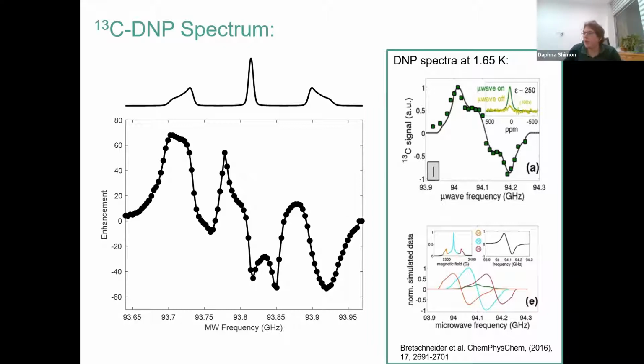And in order to understand the shape of that DNP spectrum, they were able to fit it to solid effect mechanisms from each EPR line. So you see here the blue, the central EPR line has a blue solid effect. The orange also has a solid effect, and the red. And they also included a small positive Overhauser effect coming from the central EPR line. So that suggests to us that we should be thinking about solid effect and Overhauser effect in our sample too.